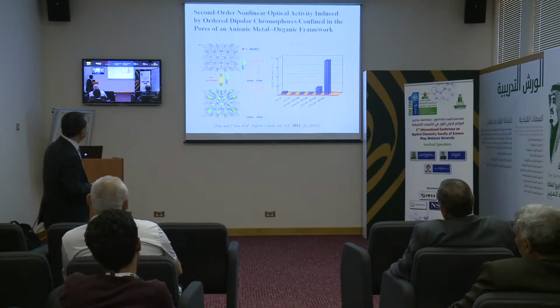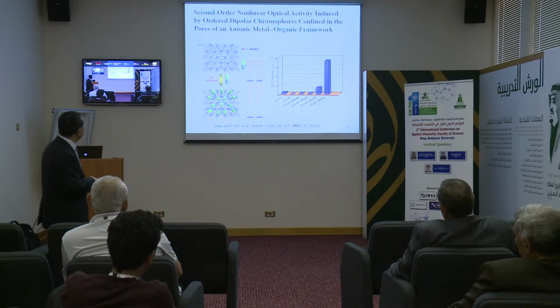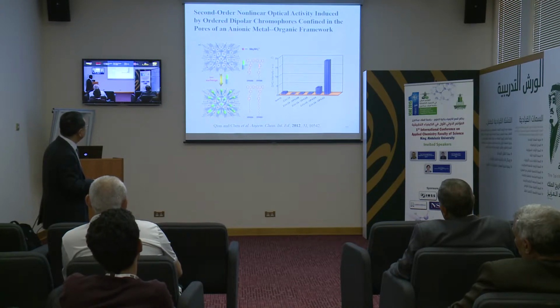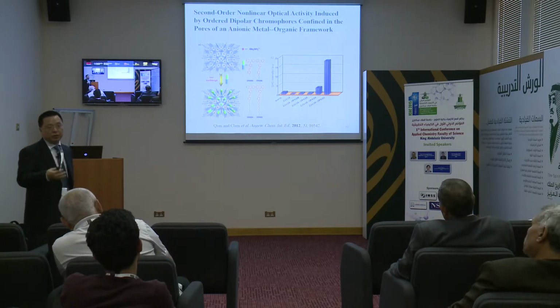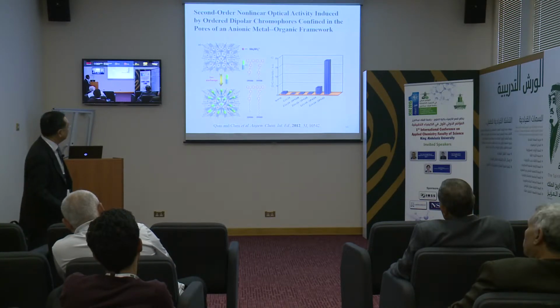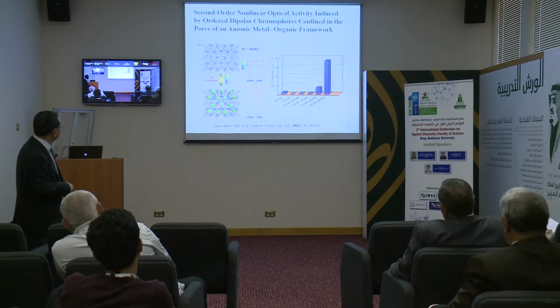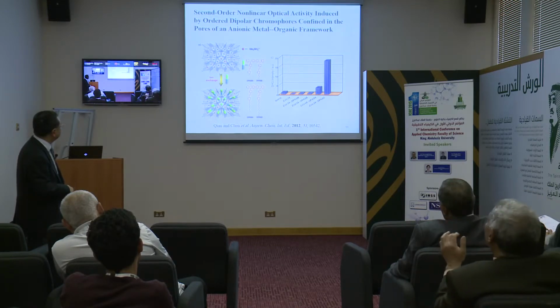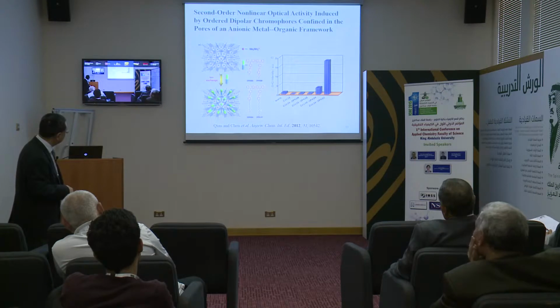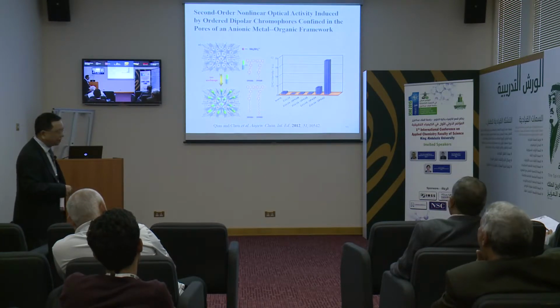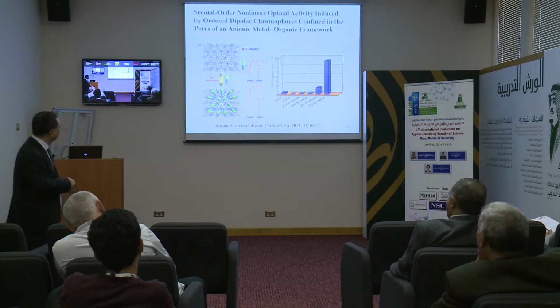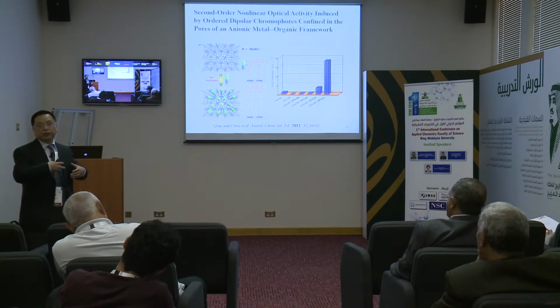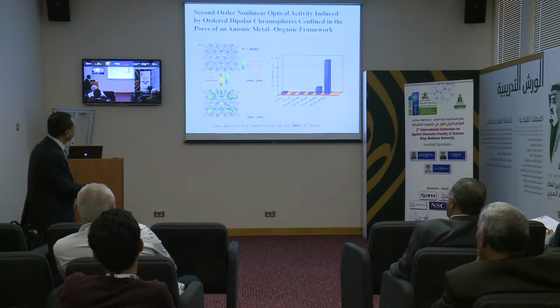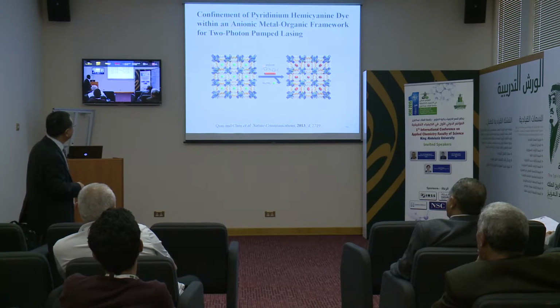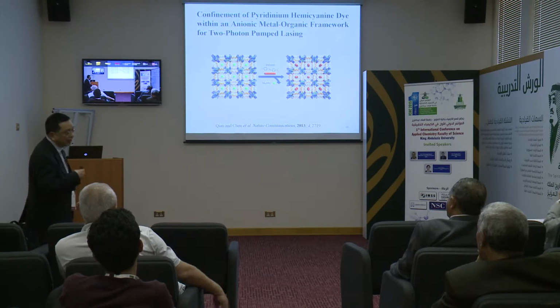And using this pore confinement, these cations can be exchanged by different dye molecules, because these dye molecules potentially have nonlinear optical properties. But apparently, these pores have different pore confinement effects. It turns out that this long alkyl chain will fit this pore, so the orientation of the dye molecule within this 1D channel is well ordered. So the nonlinear optical properties can be optimized in this case. And then furthermore, we can also use other types of dye molecules that potentially have lasing functions.